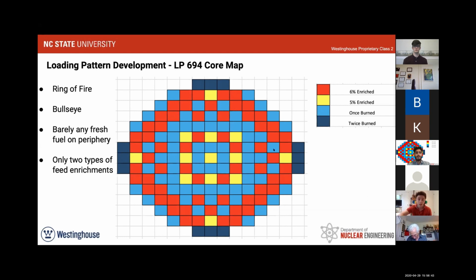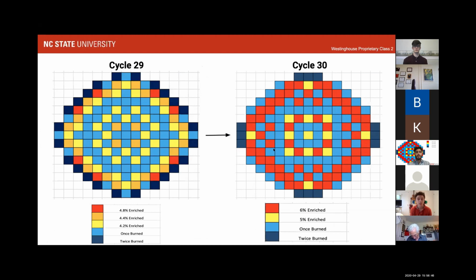And then here's a comparison of cycle 29 and cycle 30. You can see on the left is the low enriched and on the right is the high enriched. There are some interesting similarities and differences between how these cores turned out. We definitely got some good ideas on where to put our twice burned fuel. It was only really viable on the core periphery, on the outermost core positions possible. There's also a similarity where this red, our 6% ring, is about where cycle 29 had their 4.8 and 4.4 enriched.